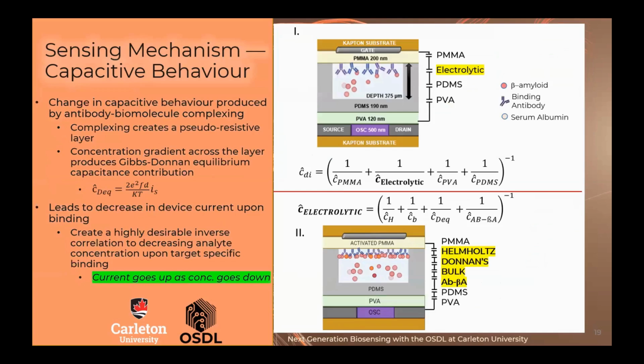The sensing mechanism, and this is where it's quite different than the electrolyte gating, right? We don't have ion exchange, we have ion separation. So if you're familiar with the Gibbs-Donnan behavior, when you have a permeable, semi-permeable to somewhat non-permeable membrane at an interface, it separates charges. So charges are not able to travel through it, which creates a capacitance effect. It's a small capacitance effect, but it primarily depends on the binding there, which creates that permeable separation. So for many, it's insignificant.